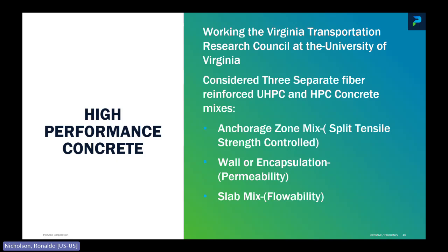The other challenge was to develop a mix that can meet all the needs. Working with the Virginia Transportation Research Council, we developed 3 separate fiber reinforced ultra high performance concrete and high performance concrete mixes, which were tested in the VTRC labs, where we were looking for different properties to give a go for that mix. For the anchorage zone, we depended on our splitting tensile strength of the control mix to make sure it was feasible. For the wall or encapsulation, we're looking more at permeability, as well as flowability at the slab mixes. All of these were in a controlled lab.